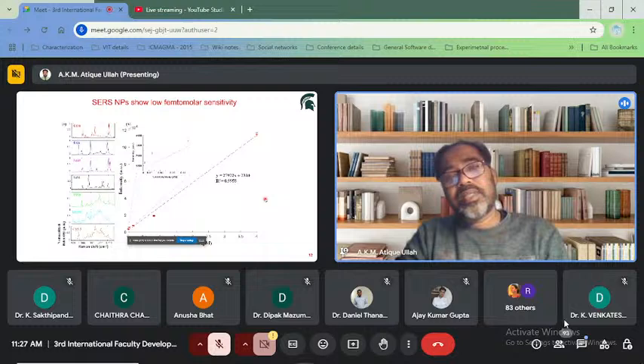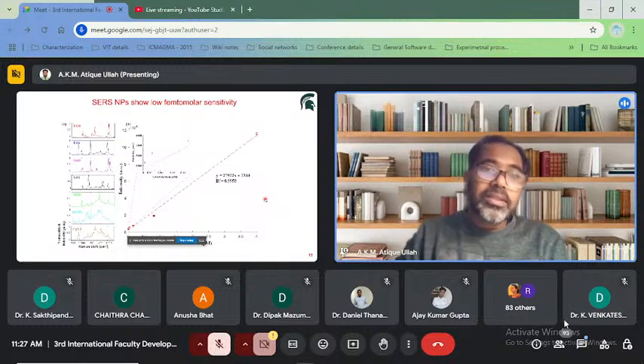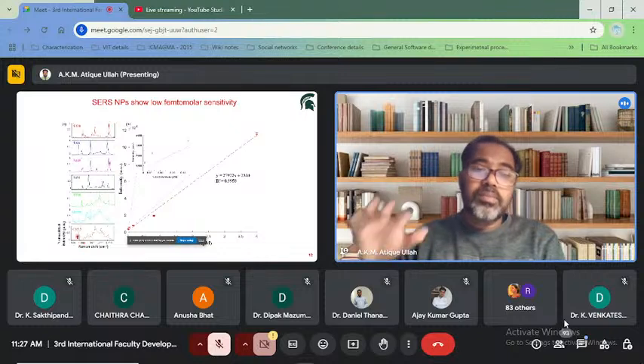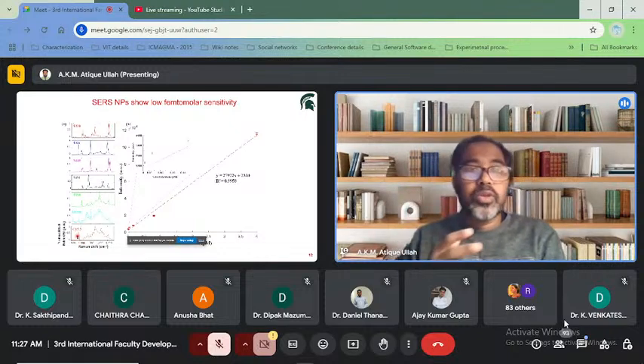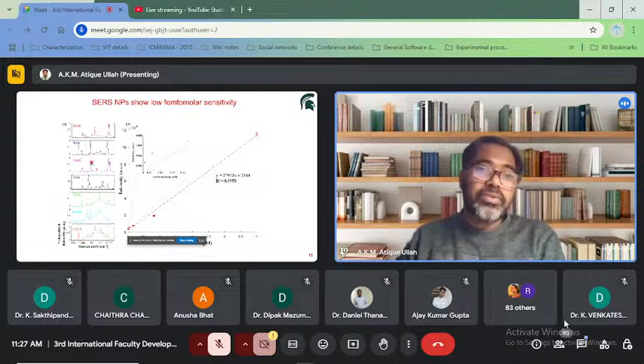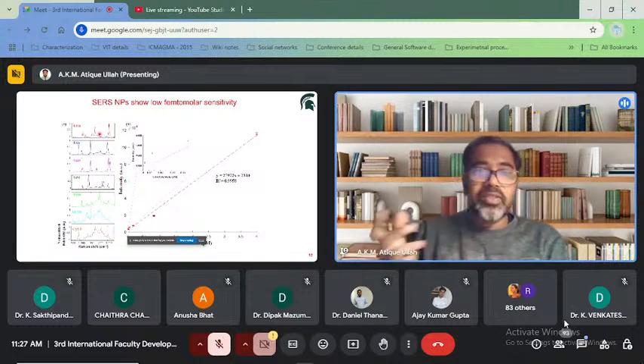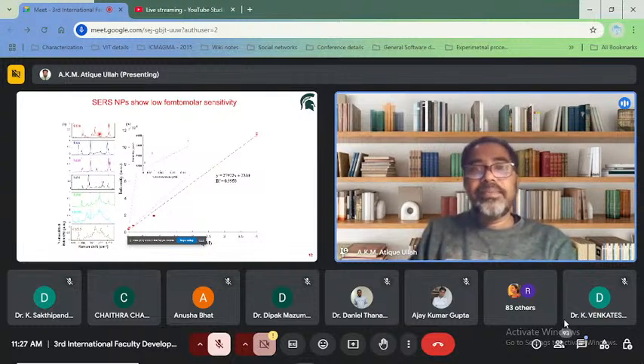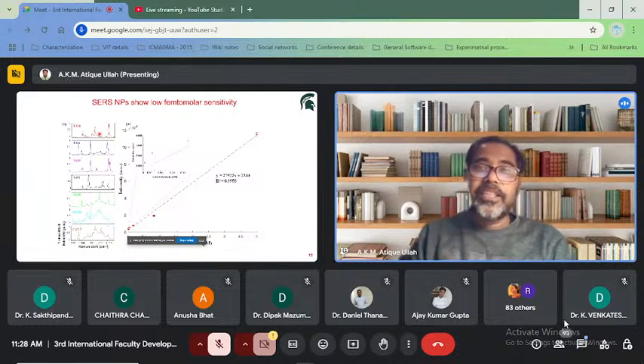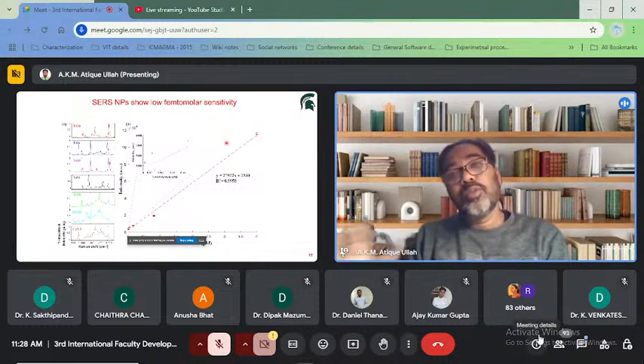Then we checked the sensitivity of our SERS nanoparticles. I already mentioned one flavor, the S420. These are the other flavors. You can see we synthesized SERS nanoparticles with different flavors: S420, S421, S440, S481, S493, IS780, and CI5.5. You can see each SERS spectrum has a unique spectral signature. Then we determined the sensitivity of our SERS nanoparticles. We figured out that our SERS nanoparticles can detect at the femtomolar level. That means our SERS nanoparticles are super sensitive. It shows femtomolar level sensitivity.